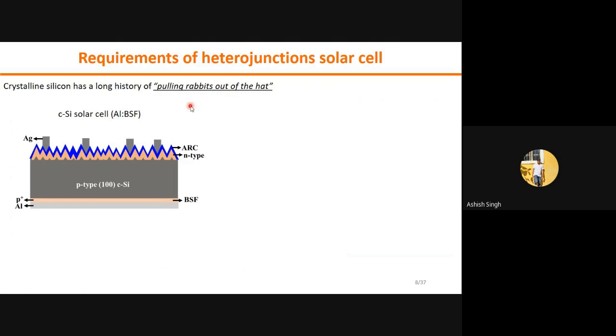If we go into specifics, the aluminum BSF solar cell is a commercialized solar cell, and this is the architecture of the aluminum BSF solar cell. If you see any installed module on a rooftop or anywhere, most of the modules will be aluminum BSF solar cells only. In this, P-type 100 silicon wafers are used for the absorber, and diffusion with phosphorus makes the N-type layer, then anti-reflection coating, and metallization on top of it. Similarly, on the back side, we need to put aluminum and do the firing. It will form the P plus layer that we call the back surface field.